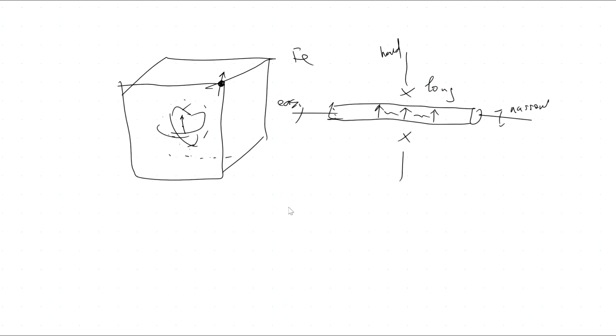So what it would mean is that even at zero magnetic field, it might stay magnetized along the easy axis. So that would be the easy axis, magnetization versus magnetic field. And at the same time, if you would like to magnetize it perpendicular to the wire, then you would have to apply a sufficiently large magnetic field.